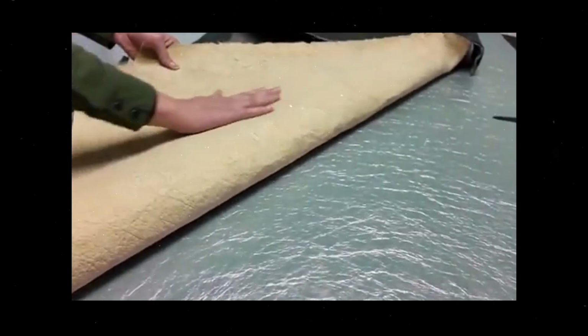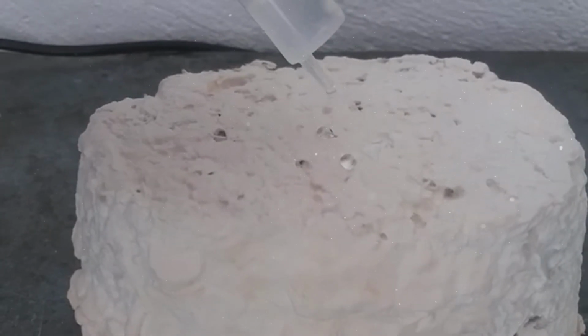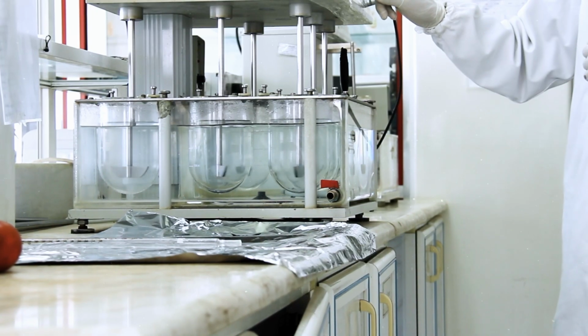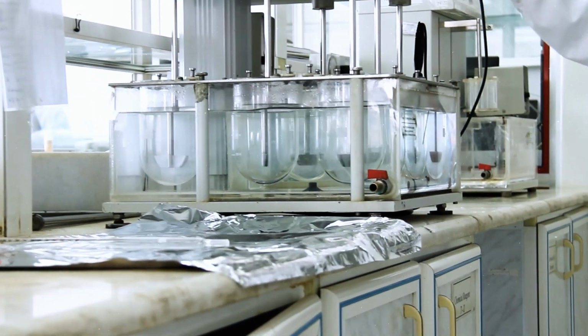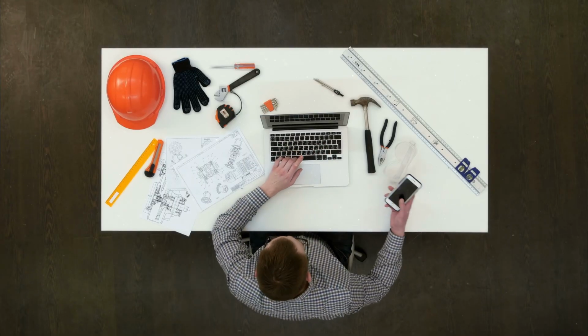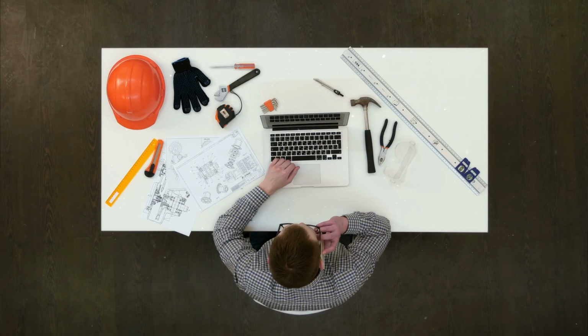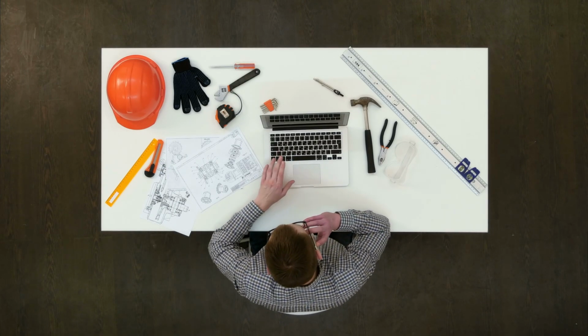The waterproofing challenge and lack of mechanical performance nearly derailed commercial viability. Mycelium can swell in humidity. Researchers explored various treatments: chitosan coatings, nanocellulose reinforcements, hybrid composites, combining mycelium with bamboo or hemp fibers. These approaches showed promise in lab settings for improving water resistance and mechanical performance, though standardizing them for commercial production remains ongoing work.